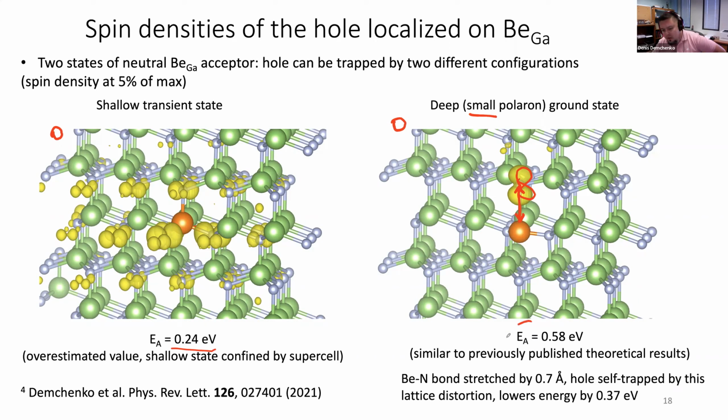This is what theory predicts to be the ground state of the acceptor. And we agree with all the theorists that did this. We get a similar result. It's just that most theorists do not predict this one, maybe because people just didn't look. They found this to be the ground state, which is correct. And this happens to be a metastable state, which they maybe just missed. But now there are two of them. So this one creates ultraviolet PL in experiment. This one does not. Why?